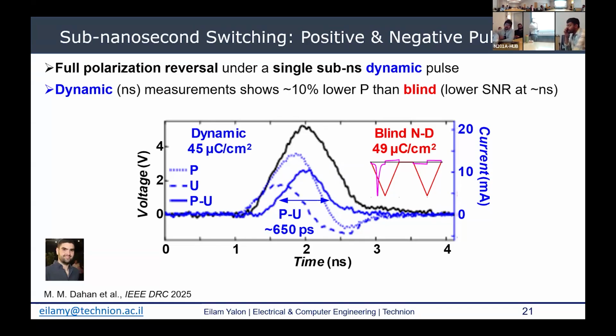This is for 4 micron by 4 micron devices. These are still fabricated by photolithography, so that limits their dimensions. And we can see that for these dimensions, we get sub-nanosecond switching. In this case, the full width at half maximum is about 650 picoseconds. If we integrate this curve, we get the polarization from the dynamic measurement, which you can compare to the polarization from the blind measurement. And there is about a 10% difference at this short time scale.